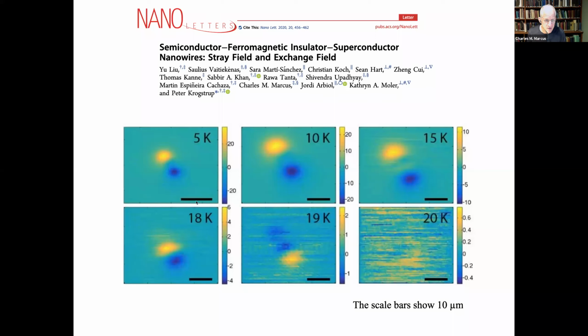This scale bar is 10 microns long, and you see that in fact there are big magnetic fields associated with the ends of the wires. So coming out of the end of the wire are magnetic fields that her team picks up on their SQUIDs. And by the time you get up to 20 Kelvin or so, the magnetism is washed out and the thing has disappeared.